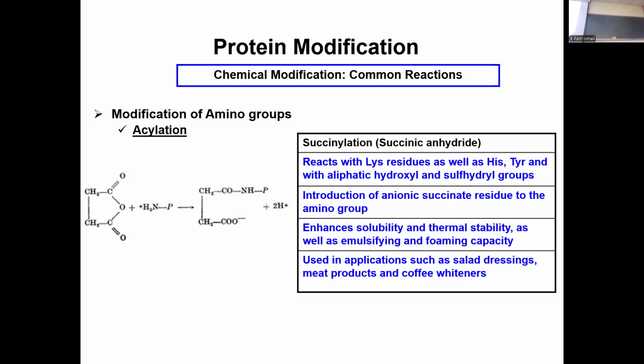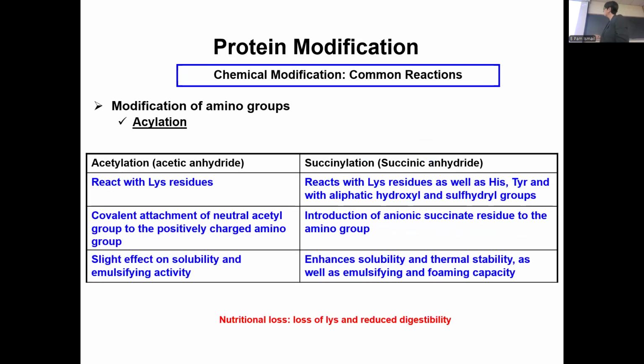And that's why I was confused by that paper, because at the isoelectric point they got better stability. How did that happen? Theory tells you the opposite. The more net charge you have on the surface, the more interaction you have with water, the less the protein is prone to open up. So it has better thermal stability. The main issue with that is the loss of lysine and reduced digestibility of the protein. So the enzyme will be less active towards that protein when it is chemically modified like that.